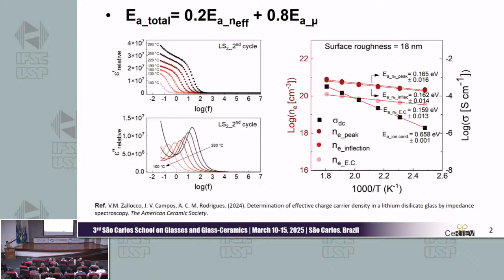On the top we have the real part, on the bottom we have the imaginary part. Using this, we were able to determine the number of effective charge carriers, as you can see on the left side. As a consequence, we found out that the increase of ionic conductivity, at least at room temperature, is mainly due to the change in mobility of these ions. More specifically, 80% of the total ionic activation energy of the conductivity is related to the mobility of these ions.